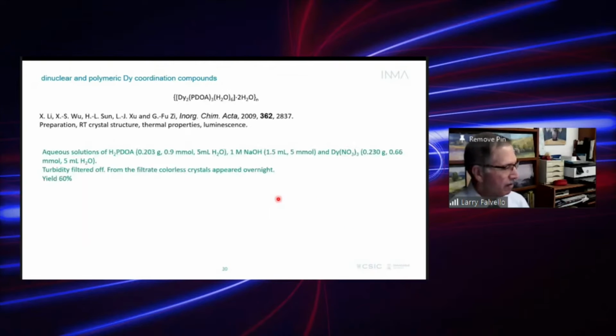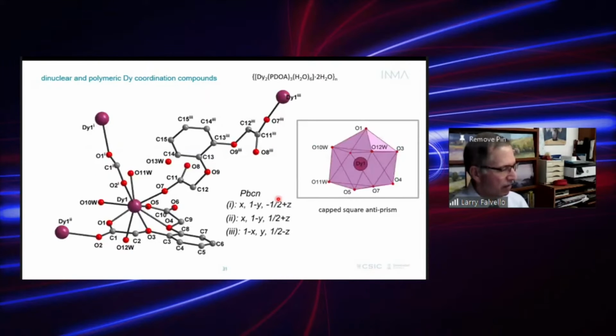Well, the first compound, the polymer, both of these have similar empirical formulas too, by the way. It was prepared in very mild conditions. You just mix everything together, filter it, and crystals appear overnight, almost a gift. Now, the structure at first looks a little daunting, but it's not so much when we analyze its components. There's one unique dysprosium atom. The space group is orthorhombic Pbcn. Dysprosium is surrounded by a monocapped